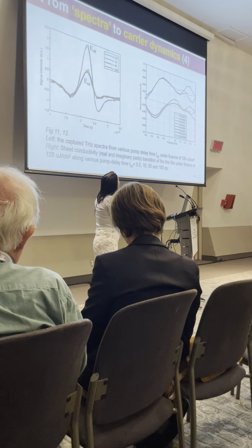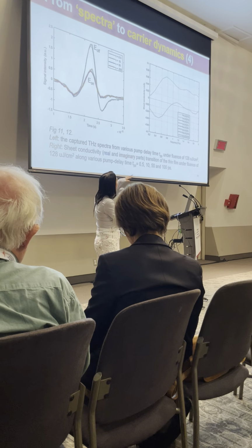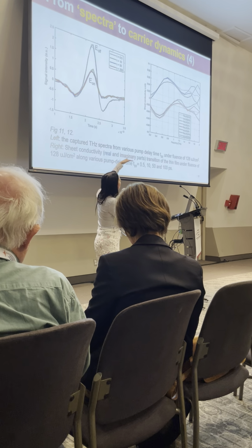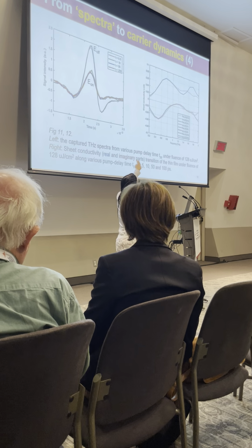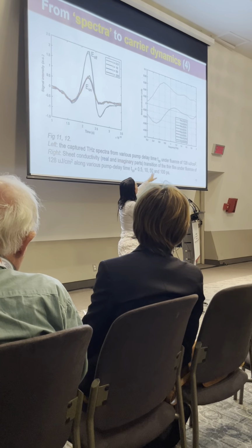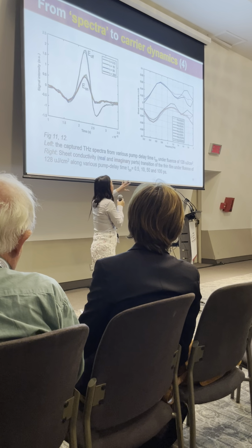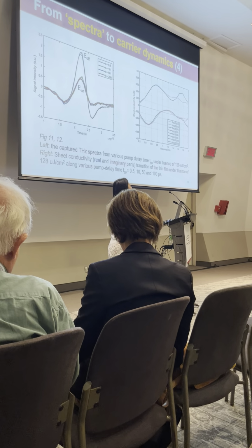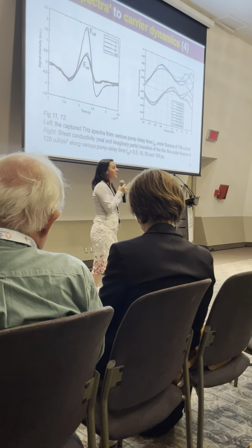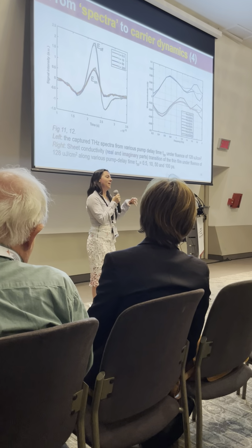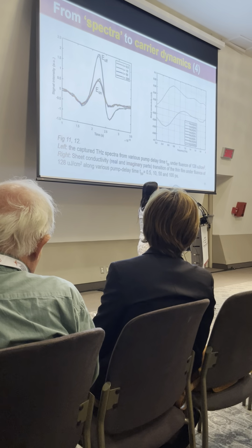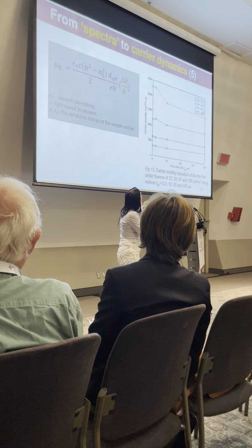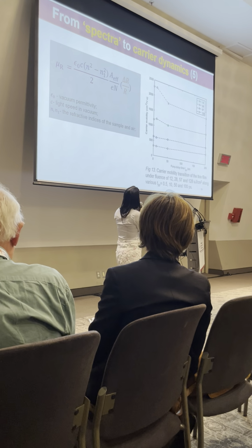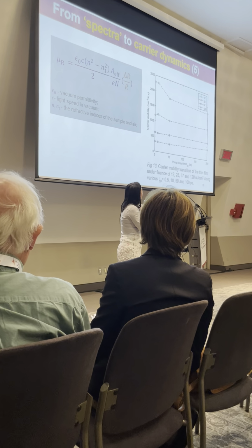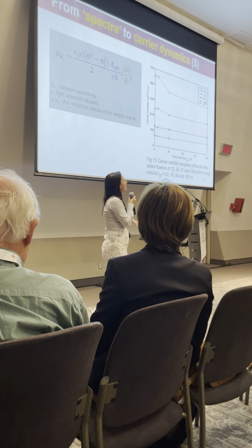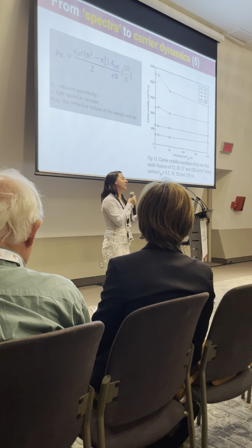So that's our next step here, but as you look at different times after photoexcitation, you can see that the conductivity is reducing, and also that crossing point that we see in the imaginary part in red is shifting as well. So that's giving us a little bit of an insight there. And we're going to look into this in a little bit more detail, about what kind of models we can fit to this spectral data to extract the scattering rates and relate that back to the carrier mobilities that we've got from the decay curves. But this is quite a nice study already in terms of looking at the mobilities and showing us about the dynamics in these thin films.